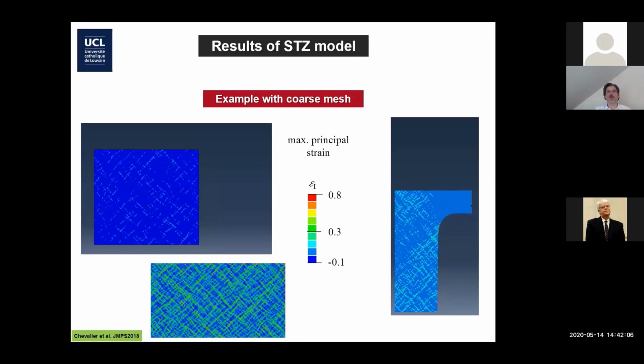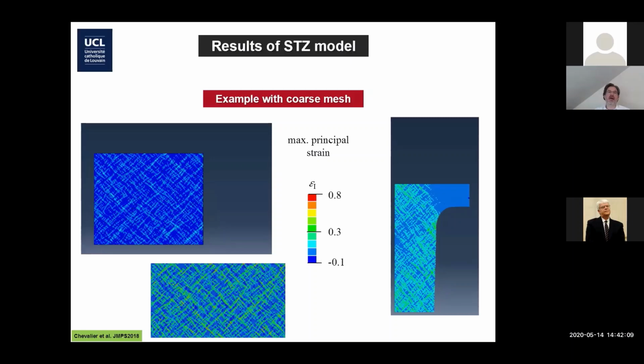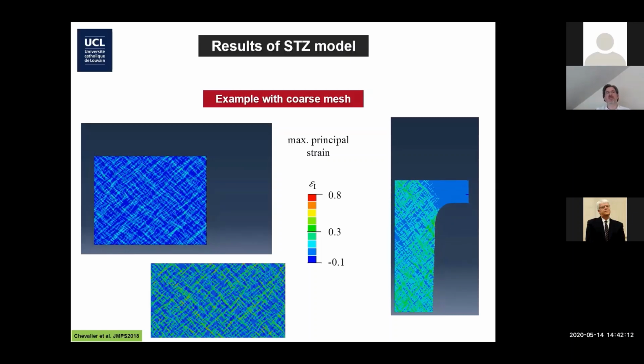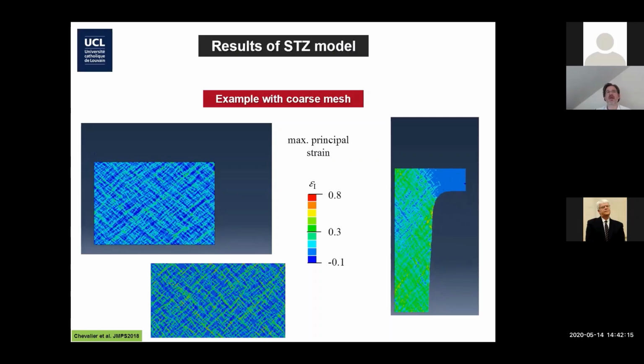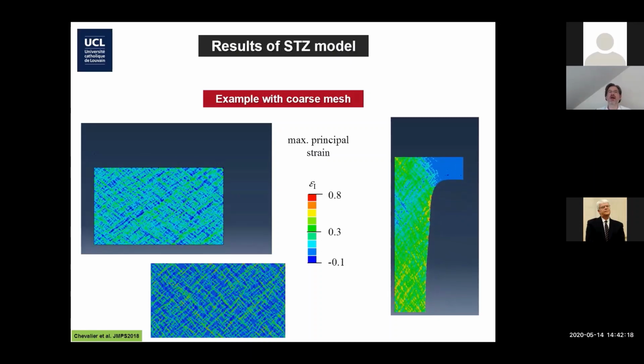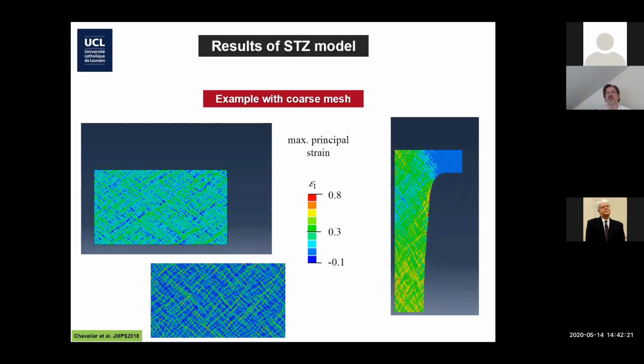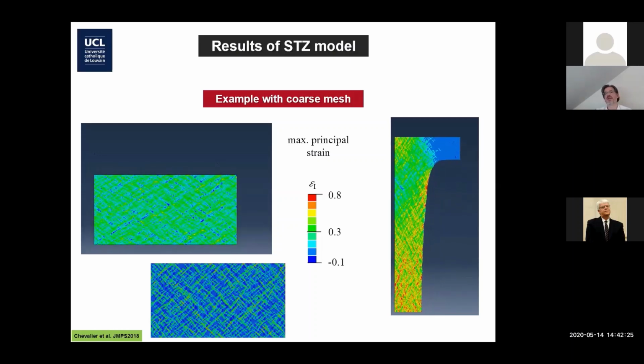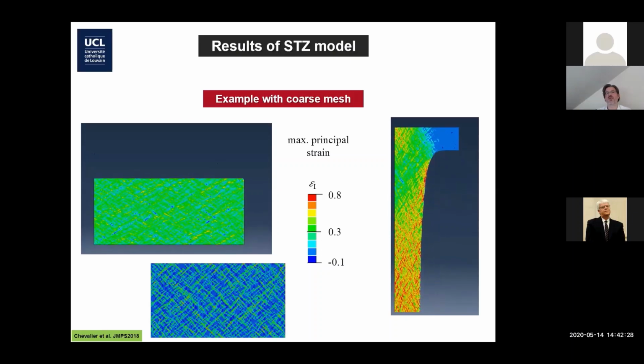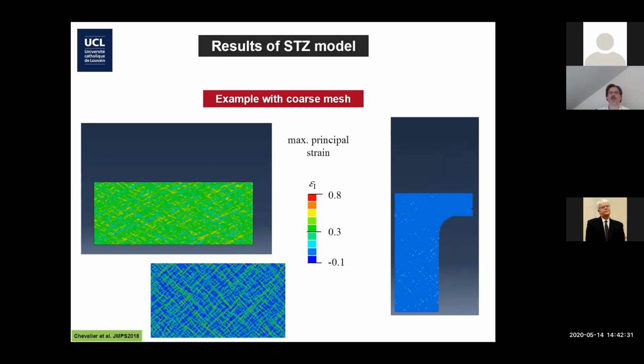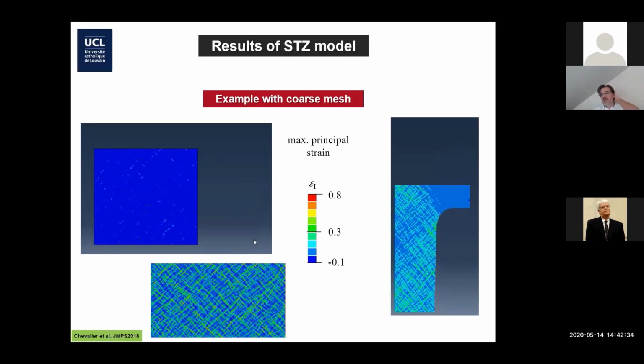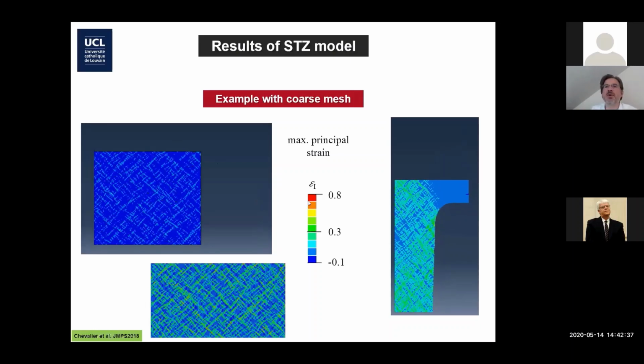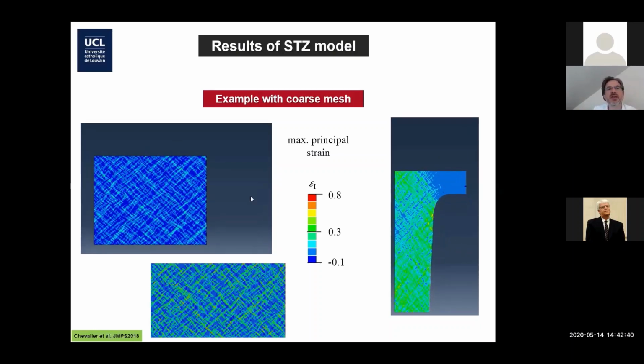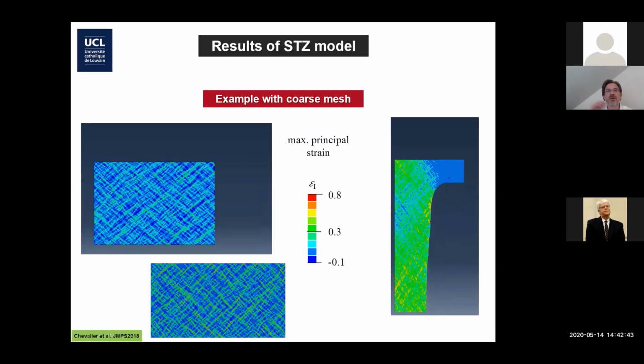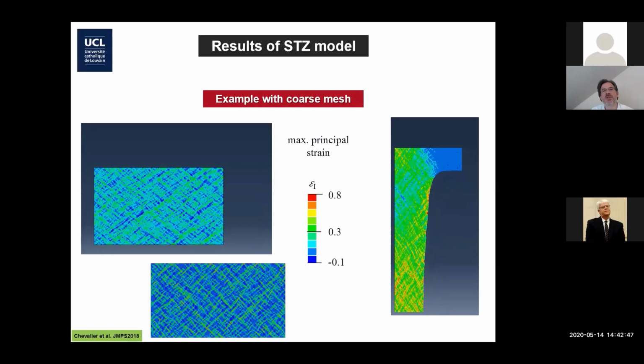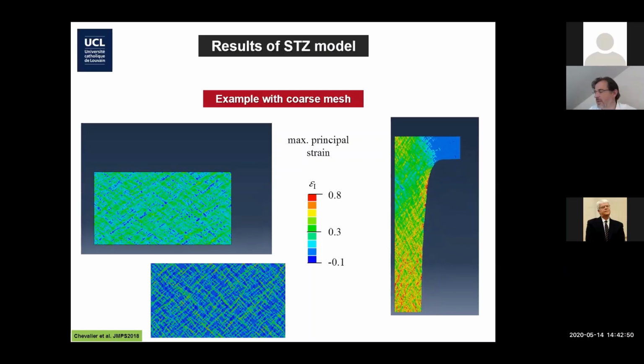Okay, so these are some simulations when you just turn the crank, and it seems easy, but there are some subtleties, and Frederick, for the time being, is spending time trying to regularize some effects of time stepping, etc. I think now we have a fairly reliable code and version that converges if we decrease the time step. You see nicely, in the little dots, the maximum principal strain plotted here, and you see the transformation starts with a few STZ, then they trigger patterns which you see directly are organized under maximum shear.